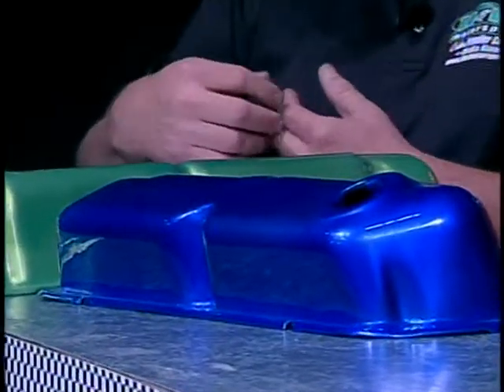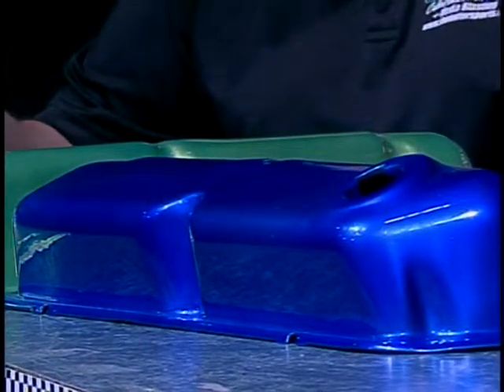But back again, how it's applied and what you do, it's a powder, like I said, it looks like powdered sugar, and it's put on electrostatically. When the powder comes out of the gun, the part has a positive charge, and the powder is a negative charge, and that's what makes the powder hold on to the part. It goes into the oven, and it's cured at 375 for 18 to 20 minutes. And at that point in time, depending on the application, if it's just a black, you pull it out of the oven, and it's cooled, it's ready to go. There's no additional cure time, no special rub outs or anything. It's ready to go. And I guess, Dan, is that what makes it so durable, the baking process?